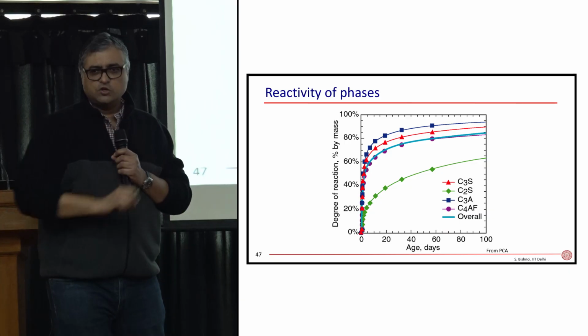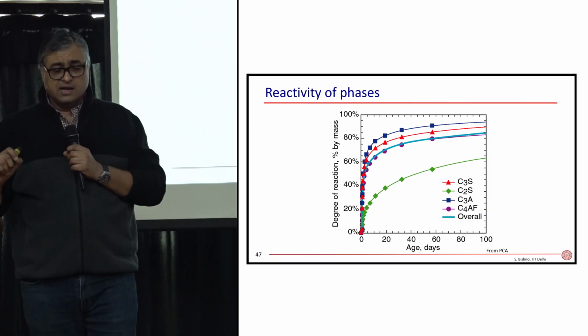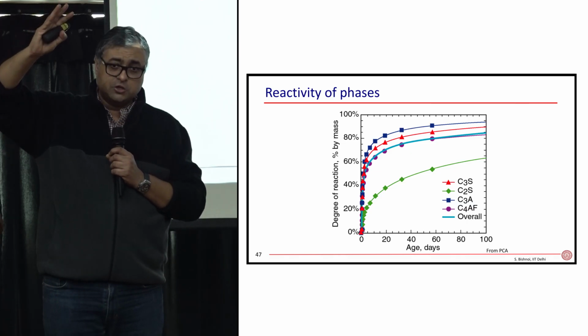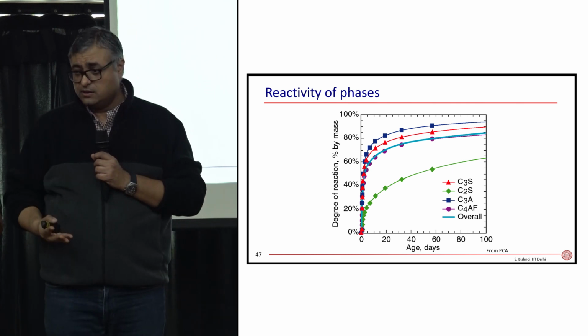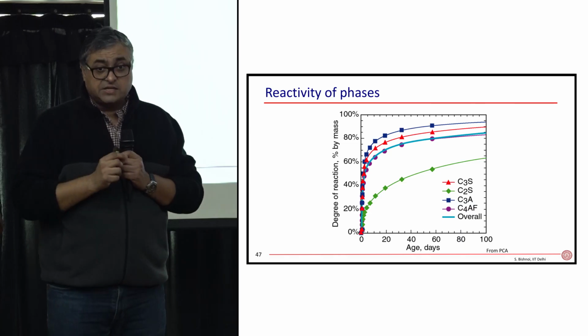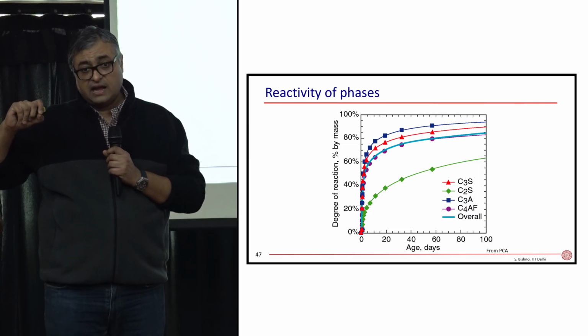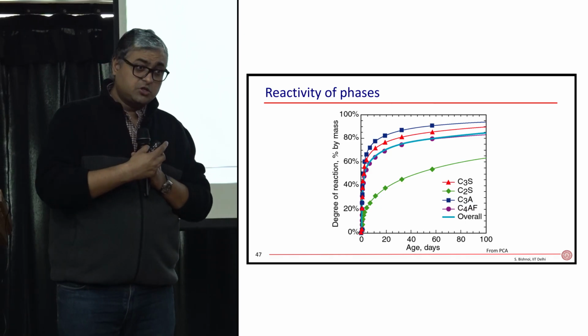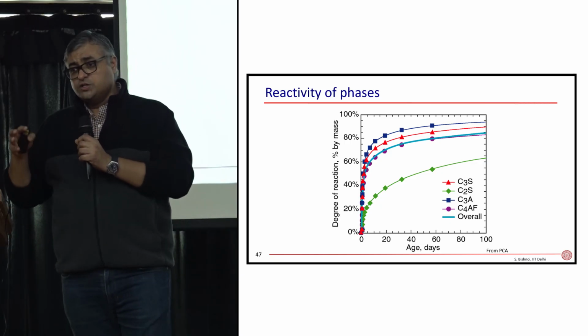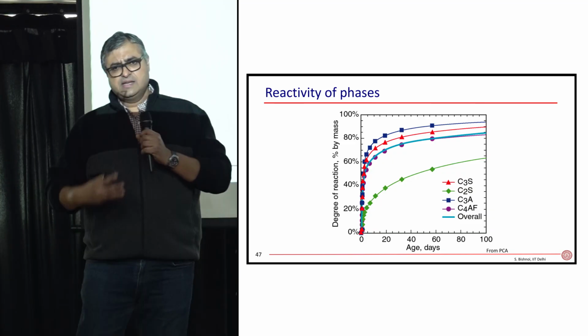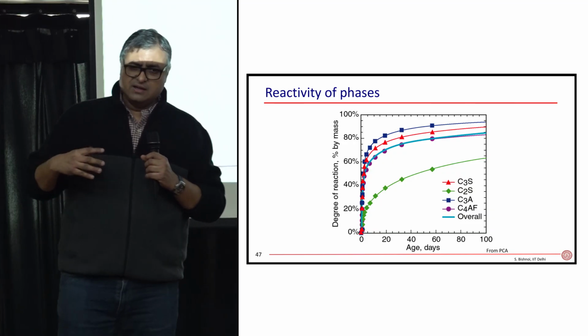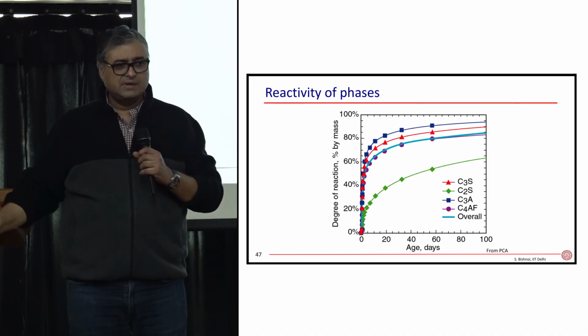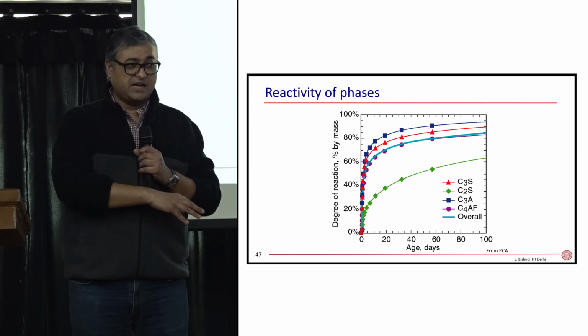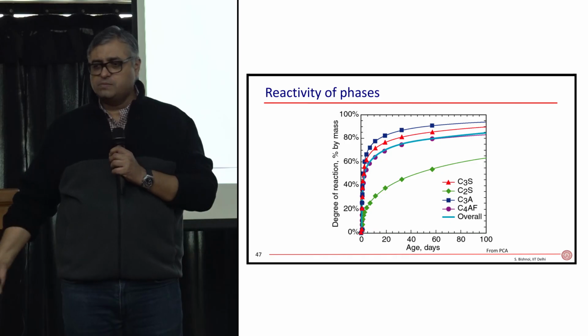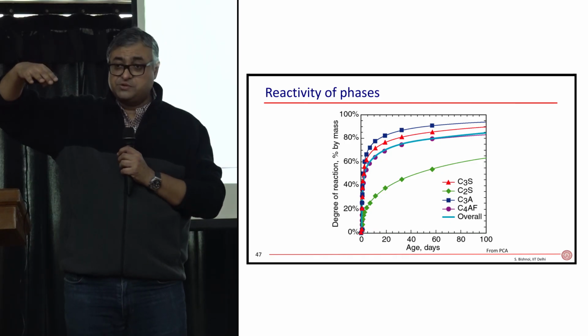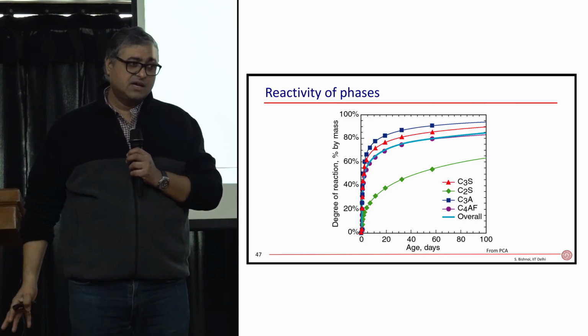You've got calcium in each of those phases. If one of those phases dissolves very quickly, like C3A, it increases the concentration of calcium in the solution and prevents the other calcium-bearing phases from dissolving. C2S, ferrite, even alite dissolution slows down if aluminate dissolves very quickly, because the calcium goes into solution already because of that. So now, because one thing is dissolving, the other can't. As long as C3S is dissolving rapidly, and there's plenty of C3S that can dissolve, C2S has no chance. It has the same ions - it produces the same ions as the dissolution of C3S. So as long as C3S is dissolving, C2S cannot dissolve because the solution is already concentrated, has a high concentration with respect to the calcium ions and the silicate ions. So it cannot dissolve as quickly.